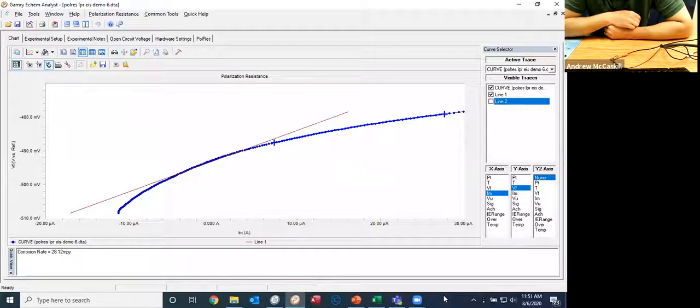But if I start going down to 0.1 Hertz, 0.01 Hertz and collecting data, then that's polarizing the electrode just as much as the LPR experiment was. So if in the LPR experiment you feel that you're actively modifying or destroying the surface, then it's probably not much different than a really low frequency EIS measurement. But it's kind of a gray area.